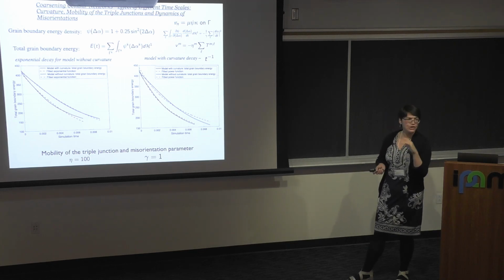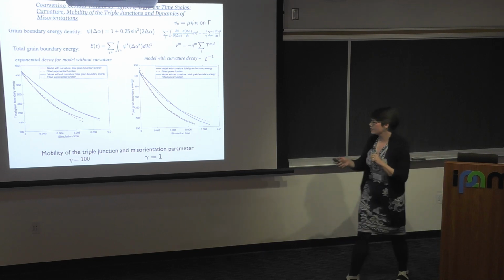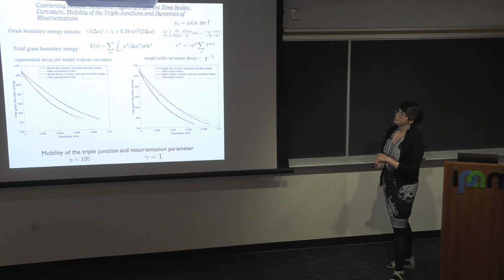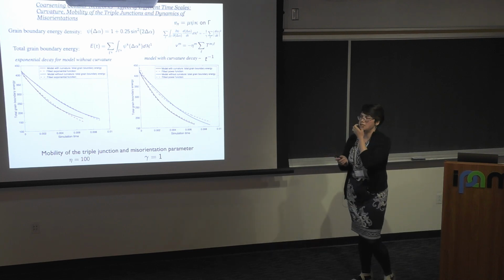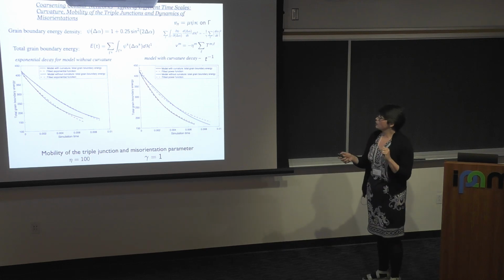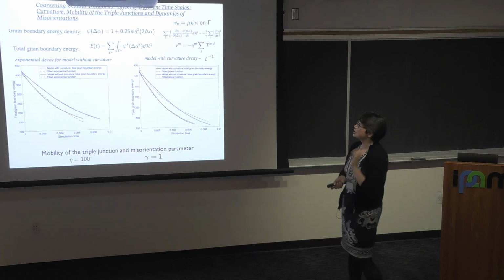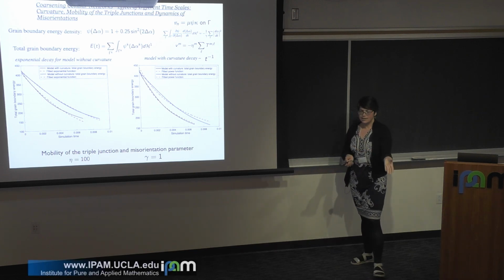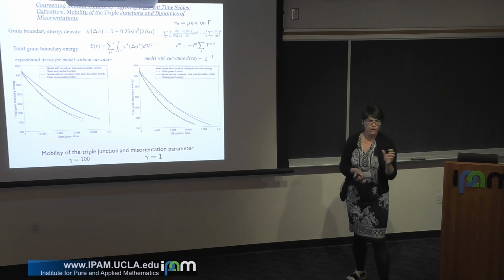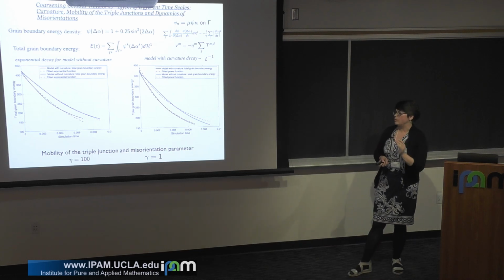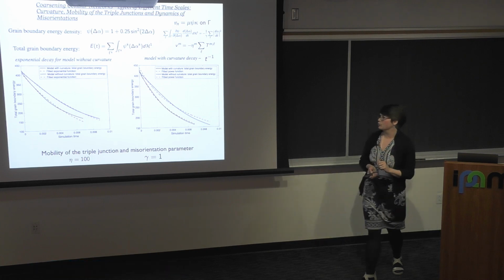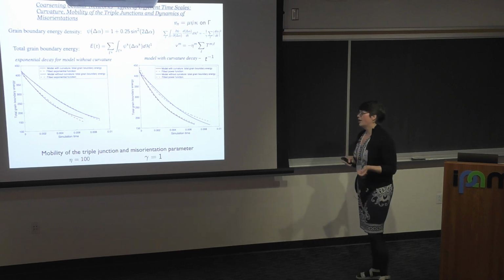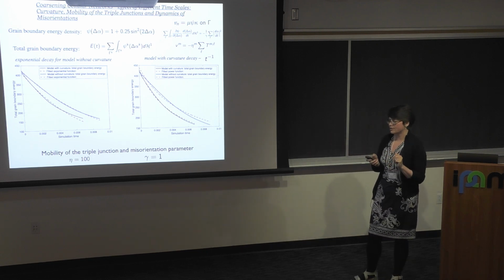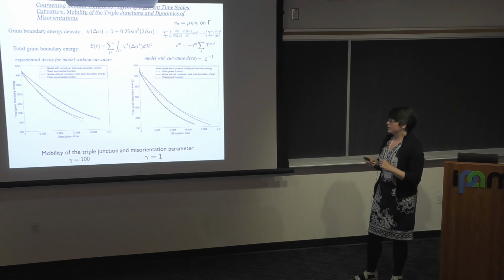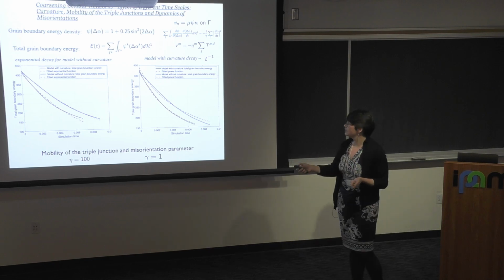Mathematically, it would be good to look at how that transition happens depending on the mobility of triple junctions. In our model, we assume it's constant. It doesn't have to be constant. But these results are also consistent with what is observed in some molecular dynamics simulations, that indeed you see the dominant effect of triple junctions during grain growth in the low mobility regime, low mobility of triple junctions. And when you go to the other limit of force balance conditions at triple junctions, you don't see any more effects of dynamics of triple junctions.